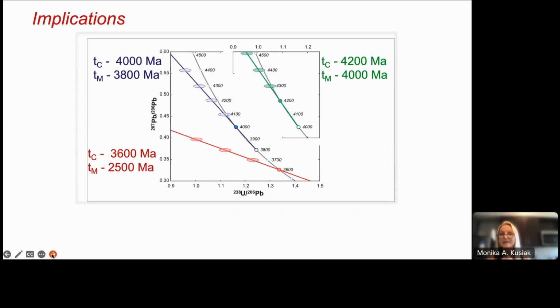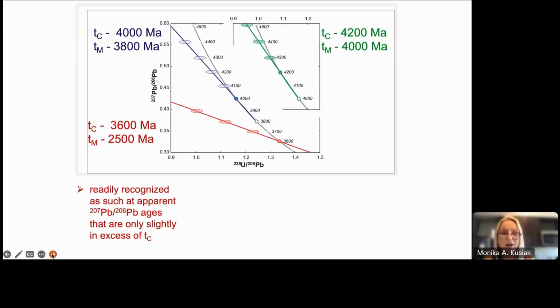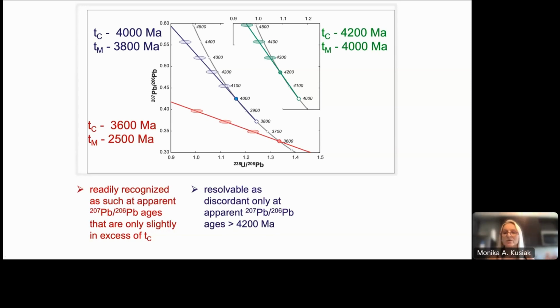Here we have 3 model examples, red, blue, and green, with a crystallization age and a possible metamorphic age. If we take a look at the red example, if we have zircons like in Antarctica, 3.6 billion years old, with metamorphism at 2.5, we immediately see something is wrong with our grains, and that reversely discordant data are an indicator of some strange process. But if we have grains which are 4 billion years old, with some metamorphic event at 3.8, then we would need data at least 4.2 billion years old to realize that we have issues with our analysis. So we can't see from the analysis, within plus or minus 200 million years, that we do not have pristine nice grains.